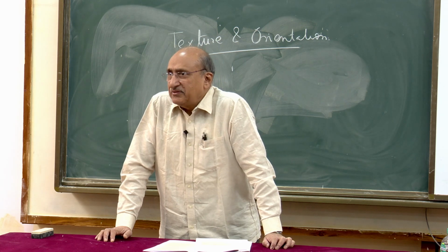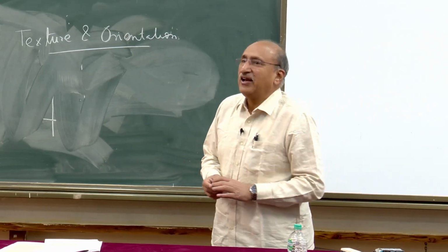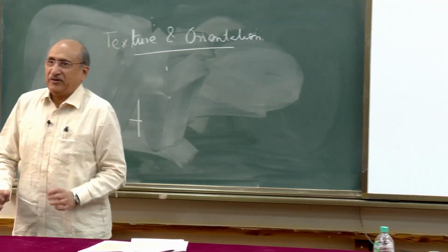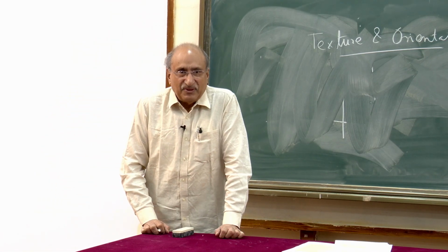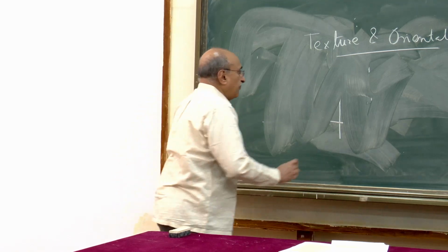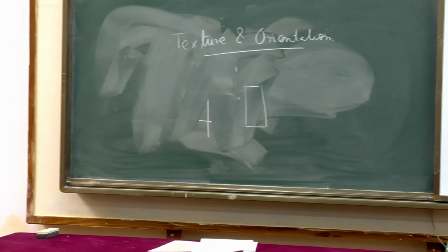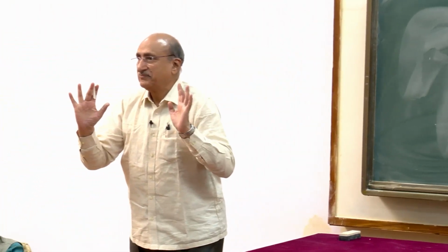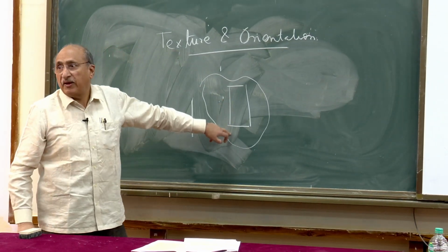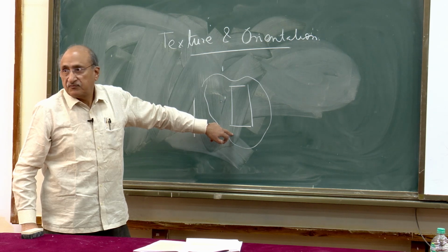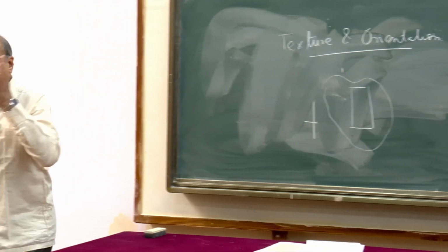I will give you an idea. These are qualitative discussions, not really quantitative, but just to give you a feel of that particular thing. And sometimes I feel that qualitative discussions give you better insight. Suppose I am writing a bit, let's suppose this much. And if I have a grain size which is bigger than the bit size, so this is my grain, I have to create a domain wall within this. And if my bit size is small, the domain wall will have to be very small. You have to work against the exchange energy.